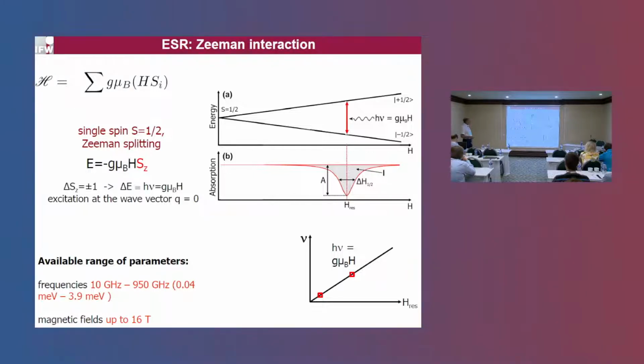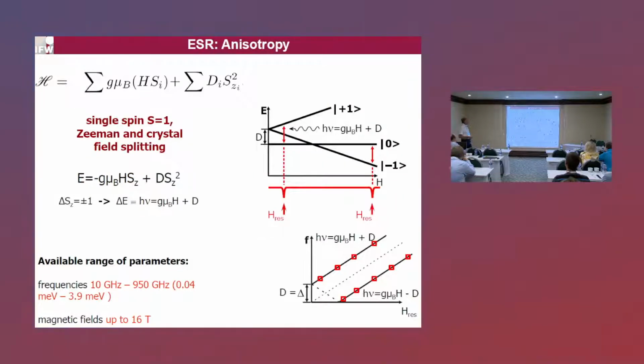Now, if the system is more complex, for instance if it has some anisotropy, the ESR response gets a bit more complicated. In that case, even in the absence of a magnetic field, some particular spin states have lower energies than others, and this corresponds to the opening of an anisotropy gap. The ESR response gets more complex: instead of a single line, in this particular case one observes two lines. If one measures these signals at different frequencies, one obtains two resonant branches. And if one extrapolates them to zero magnetic field, one directly obtains the excitation energy in the spin system.